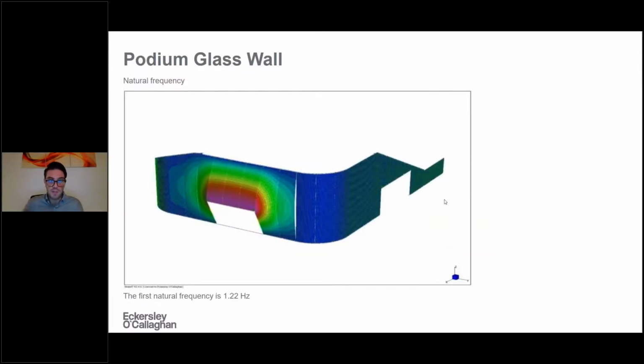From a natural frequency point of view, the code set a limit of 1 Hz to avoid further dynamic studies on the facade. In the very conservative scenario of just the pre-stress of the rod, the facade was having a natural frequency of 1.22 Hz, so above this threshold of 1. But it's worth noting as well that during the wind tunnel testing, as I said before, we had to feed also some model information. So we were already accounting for some dynamic factor, from the basic pressure values coming from the wind tunnel to the more advanced and refined ones that we were given when studying the facade as a single element, let's say.